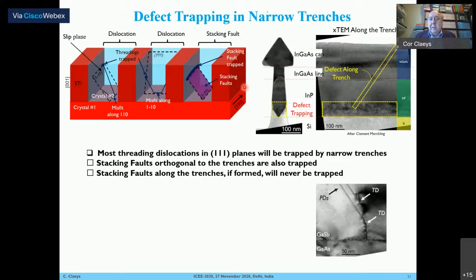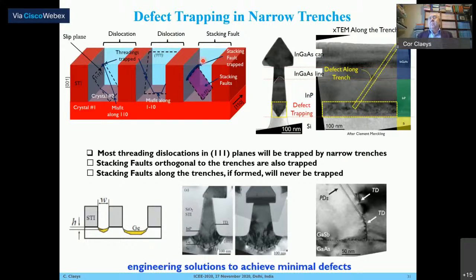An elegant way to do that is relying on what is called aspect ratio trapping for the epitaxial growth. That means you're starting with shallow trench isolation, where you've got oxide and silicon areas. You're etching away the silicon, and then you're growing in those areas your germanium or your III-V material. As I mentioned, you have to be careful with defects. One type of defect is lying at the interface, the misfit dislocations. Another type of defect are the threading dislocations coming to the surface. The third type of defects are what we call the planar defects, like for instance, stacking faults. And that means you have to optimize your epitaxial process in order to control the defect generation.